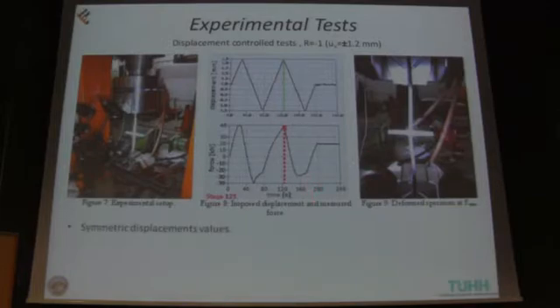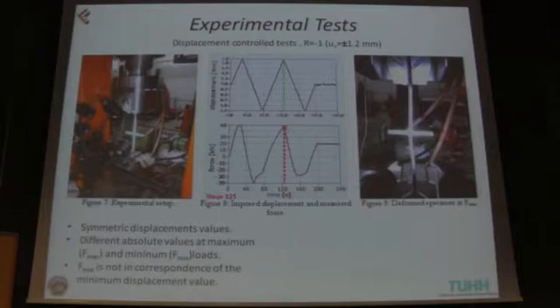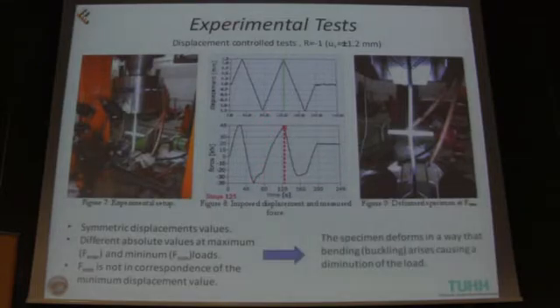It's possible to observe that symmetric displacement values arise, but at the same time we observe different values of maximum and minimum load. Moreover, the minimum load is not in correspondence of the minimum displacement. This means that the specimen deforms in a way that bending arises, causing a diminution of the load. It's also possible to see this from these figures at the minimum load.